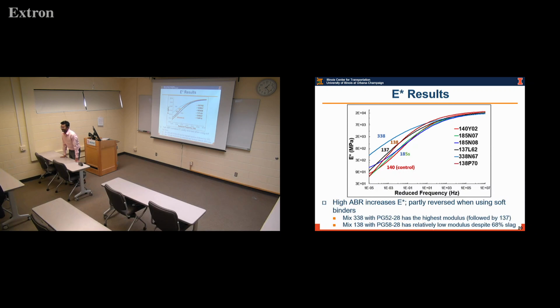The FAM, fine aggregate matrix? Did you assess how much of it is aggregates and how much of it is binder? No, quantitatively we don't have the percentage, but most of the time I would assume we are talking about 95%. I would be very confident to see 95% that is binder and the mastic itself.